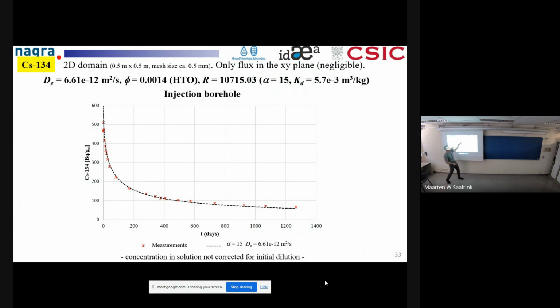That's just a transfer parameter. Of course, the retardation is huge. So KD, if it was something like 10 to the minus 5 for sodium, it's 10 to the minus 3 for cesium. So actually, the apparent diffusion coefficient is very small. The transport distances are small because of the large retardation.